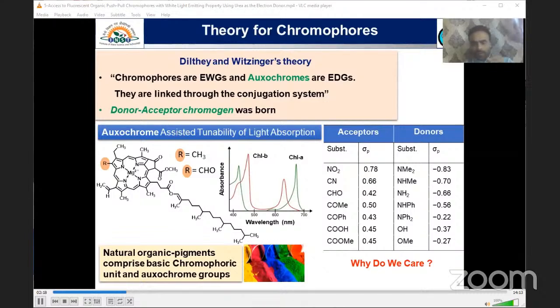Since we know that different donor functional groups and different acceptor functional groups have different Hammett constant values, which is the parameter set by physical organic chemists for determining the reactivity of different organic molecules. Here you can see that the nitro group has a para-substituted Hammett constant value of 0.78, and the NMe2 group has a para-substitution Hammett constant value of minus 0.83, which is the highest known value for the reactivity in terms of its reaction in cycloaddition reactions.